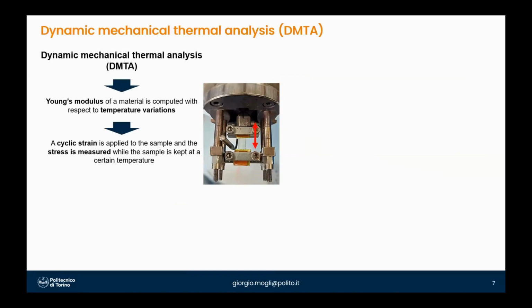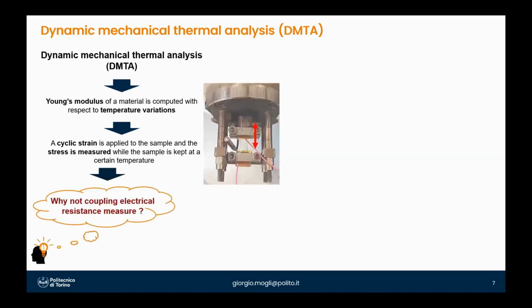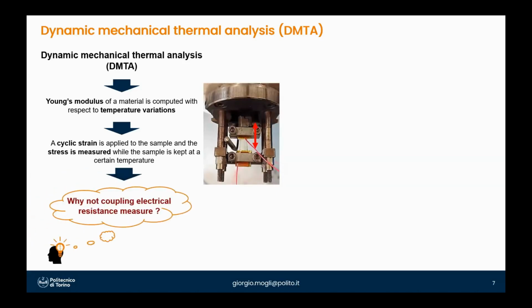This analysis is called dynamic mechanical thermal analysis, DMTA, in which the Young's modulus of the samples, which are clamped in this manner, is evaluated while the temperature is changed. This machine allows applying small strain to the samples, and the samples are maintained in a closed chamber with controlled temperature. So the idea was to couple this measure with an electrical measure by applying two electrodes to the samples.